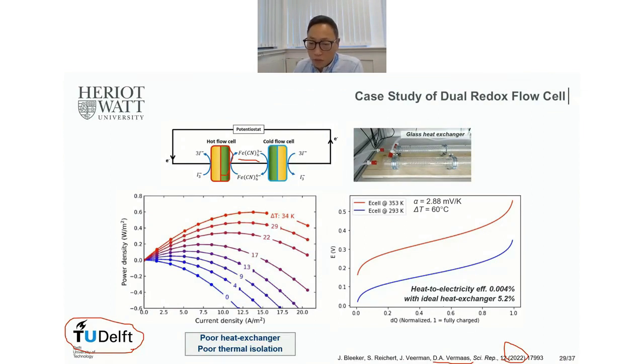But unfortunately, their conversion efficiency is only 0.004%. Quite an interesting point is that if the heat exchanger efficiency were ideal, they could reach 5.2%. So this experimental study highlights how important it is to have a good heat exchanger system. Overall, the poor heat exchanger and the poor thermal isolation of the system were the bottleneck of this case study. As you can see here on the top right side, their heat exchanger system was a glass heat exchanger without any heat isolation of this tube on the outer side of the glass tube. So naturally, they had a huge amount of heat just wasted to heat up the air outside.